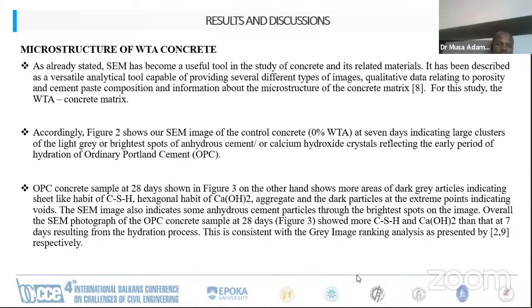OPC concrete at 28 days, shown in figure 3, on the other hand, shows more areas of dark gray particles, indicating sheet-like habit of CSH, hexagonal habit of calcium hydroxide, aggregate, and the dark particles at the extreme point indicating voids. The SEM image also indicates some anhydrous cement particles throughout, the brightest spots on the image. Overall, the SEM photograph of the OPC concrete at 28 days shows more CSH and calcium hydroxide than at 7 days, resulting from the hydration process.